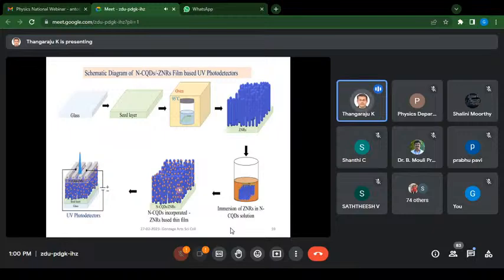So this shows that the immersion time is varied. Variation of the immersion time means the increased immersion time shows the incorporation or the absorption of the carbon quantum dots onto the zinc oxide nanorods. So the nanorods immersed into the carbon quantum dots make carbon quantum dots adsorbed zinc oxide nanorods. This structure is used in the UV photo detectors.